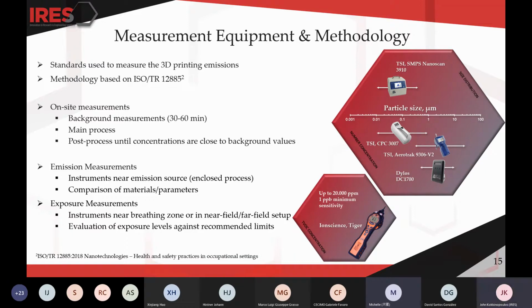Measurement campaigns are categorized into two types: emission and exposure. For emission measurements, the instruments are placed near an enclosed emission source, and the goal is to compare different materials and parameters. On the other hand, exposure measurements are performed with instruments near the operator's breathing zone or located in a near-field, far-field configuration. From exposure measurements, we can evaluate the risk by comparing the exposure levels with the respective limits.